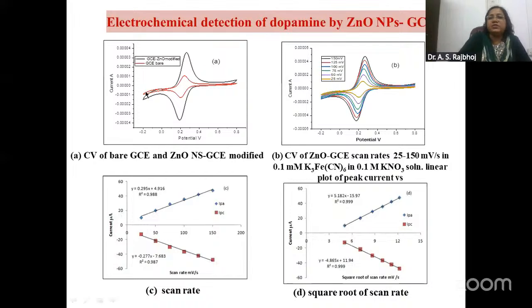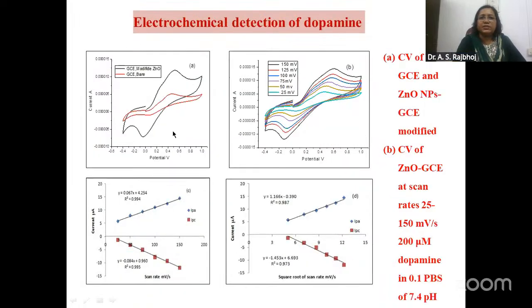You can see here the electrochemical detection of dopamine has been done using zinc oxide nanomaterials and glassy carbon electrodes. In the first panel, A, the red line is the bare glassy carbon electrode, without zinc oxide nanomaterials, and the blackish or bluish one is the glassy carbon electrode modified by zinc oxide nanomaterials. In B, you can see at different scan rates the same experiment being carried out, where the scan rate varies from 25 to 150 millivolts per second in 0.1 molar potassium nitrate solution. From A and B we have plotted the graphs against scan rate: graph C is for A, and D is obtained from B. In this way, we have done the electrochemical detection study of dopamine.